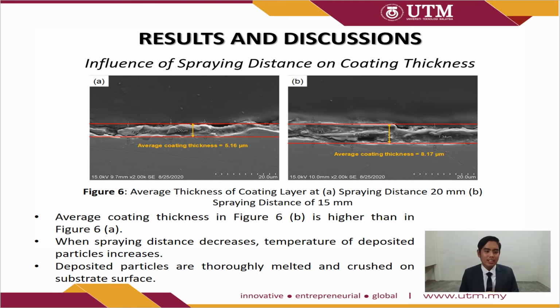Then we will be discussing the influence of spraying distance on coating thickness. As we can see, figure 6A indicates the average thickness of coating layer at spraying distance of 20 mm, while figure 6B represents the average coating thickness at spraying distance of 15 mm. The average coating thickness in figure 6B is observed to be higher than in figure 6A.